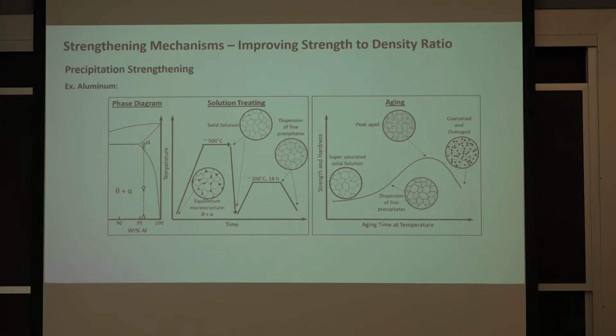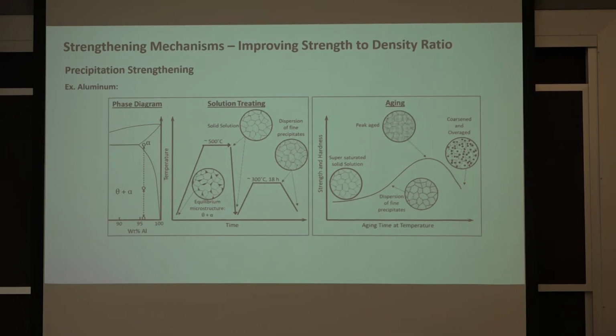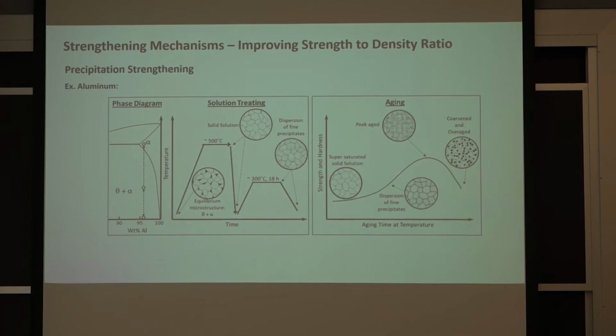These little coherent structures are very difficult for a dislocation to either penetrate and cut through or move around. When they're small and coherent, the dislocations cut through these precipitates, and it takes a lot of energy. That's why it's very possible to get a very high increase in the strength of aluminum, because it takes so much energy for these dislocations to cut through these little precipitates.